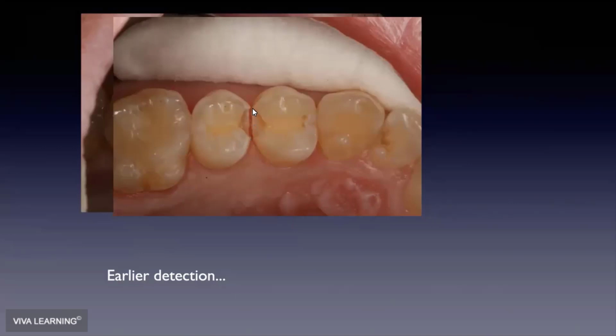Again, the only reason that I have broken contacts here is because the decalcification from that zone of caries extended to that. If it wasn't past that, I wouldn't absolutely have to break contact. But I'm a firm believer in removing all compromised or decalcified enamel so that my outer bond, which is my hermetic seal, is to the best quality enamel possible.